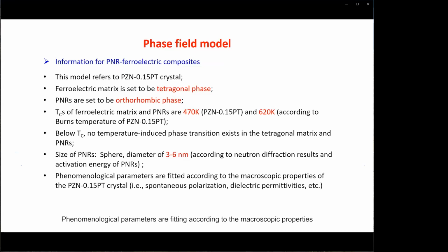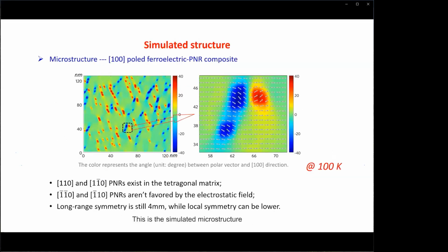Phenomenological parameters are fitted according to the macroscopic properties of the PZN-0.15PT crystals, for example, the spontaneous polarization and dielectric permittivity at room temperature. This is the simulated microstructure for a [100]-poled ferroelectric-PNR composite at 100 Kelvin. The color represents the angle between the polar vector and the [100] direction. In order to minimize the electrostatic energy, only polynanoregions with the polar vector of [110] and [1-10] exist in the tetragonal ferroelectric matrix. The macroscopic symmetry of the composite is still 4mm, but the local symmetry could be very low in specific polynanoregions, as shown here.